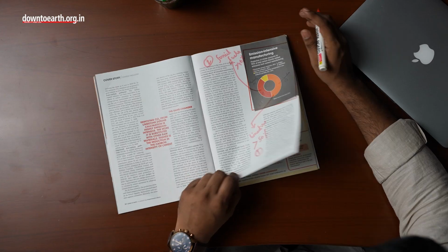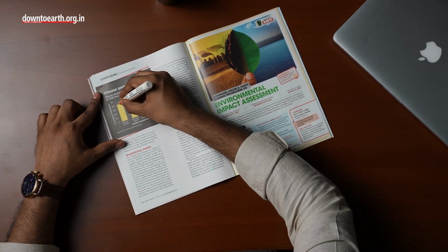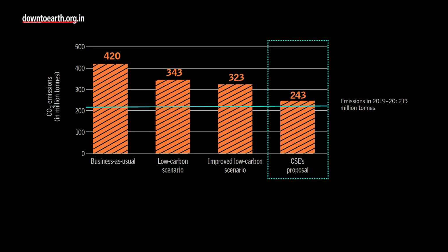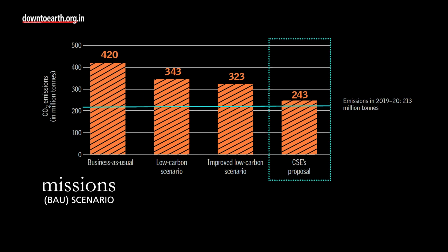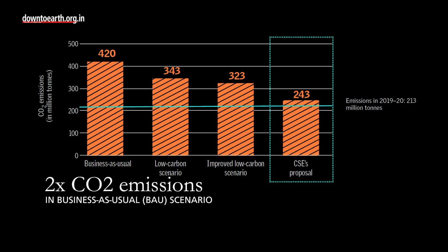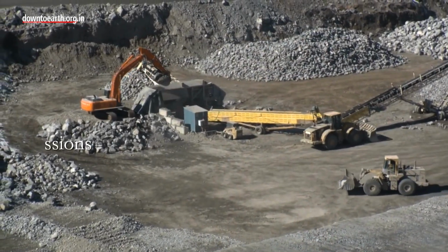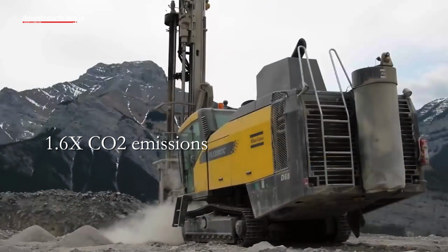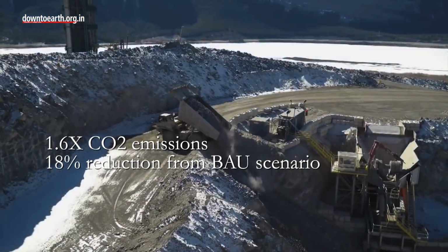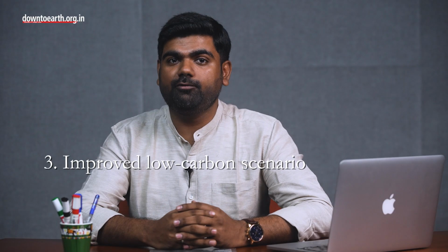CSE has projected 4 CO2 emission scenarios for the year 2030. First is the business as usual or the BAU scenario. This is based on emission factors of 2019-20 and estimated production of cement in 2030. As per this scenario, CO2 emissions from the sector are projected to grow almost twice within this period. The second scenario is the low carbon growth scenario. This scenario is based on past emission reduction intensity achieved between 1996 and 2017 and the estimated production of cement in 2030. As per this scenario, the CO2 emissions will increase 1.6 times and show a reduction of 18% from the BAU scenario.